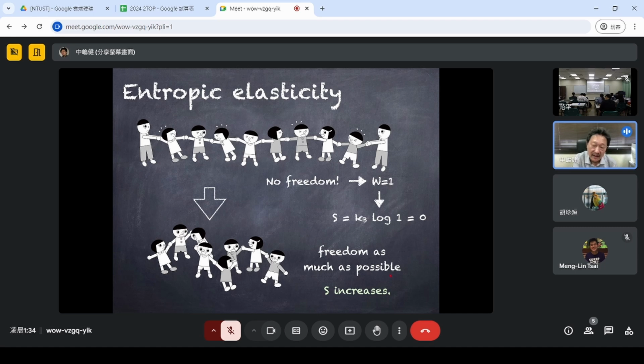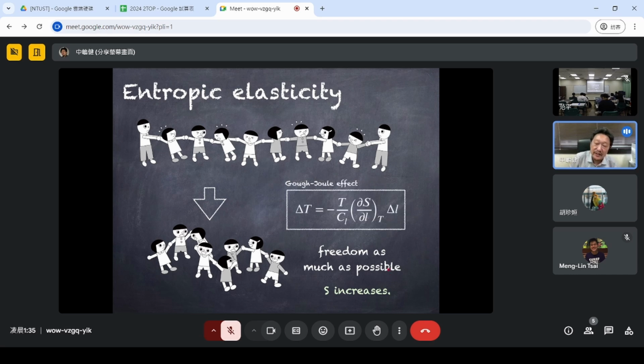That's the reason why the rubber shrinks when you release the force. So we call the elasticity of rubber rubber elasticity, but its original mechanism comes from the entropic elasticity of a single polymer chain. Okay, and starting from this idea, the Gough-Joule effect can be calculated in this manner. I will not go into the detail of that, but the temperature difference delta T is of course correlated with how much you elongated the rubber band. But the most important quantity is S here. So the change in S due to L can be correlated with this temperature change. This is what I first wanted to deliver to you in this lecture.